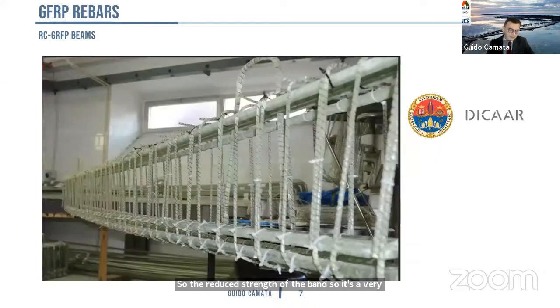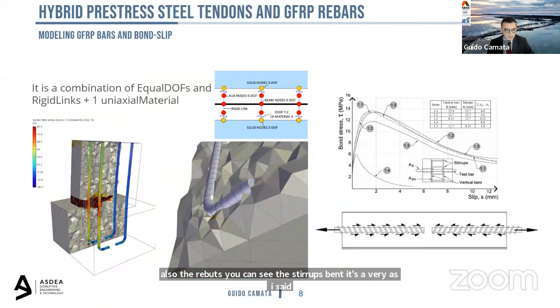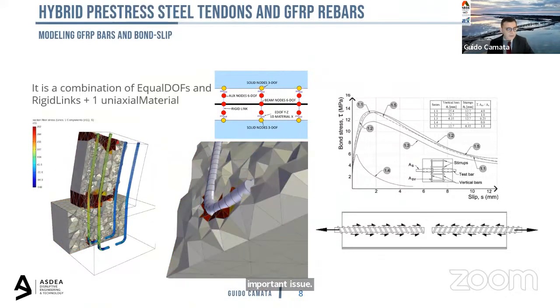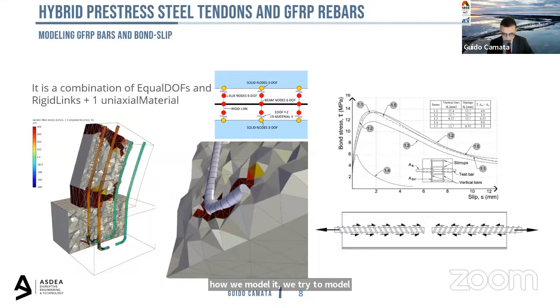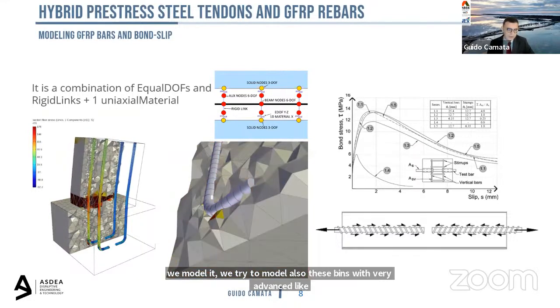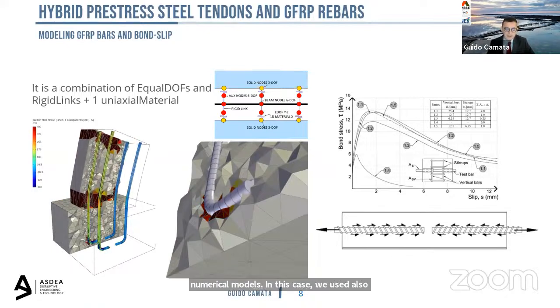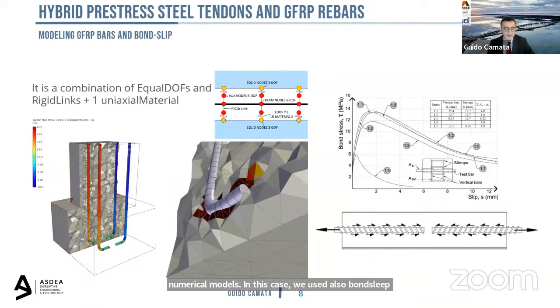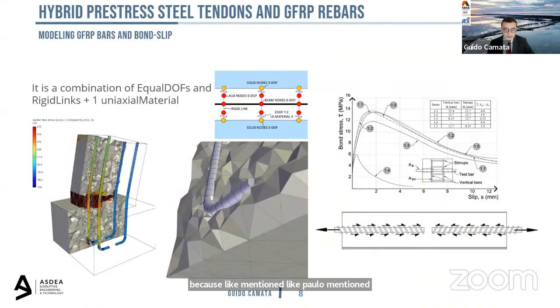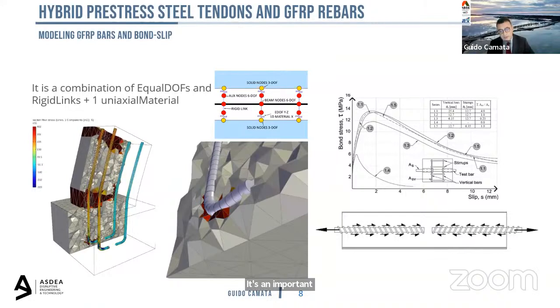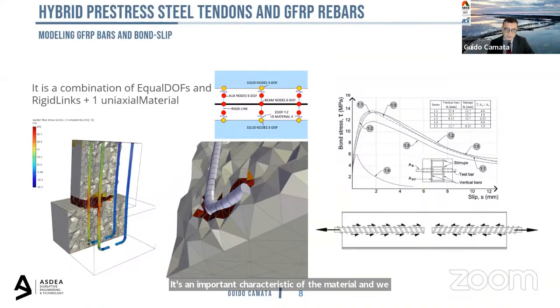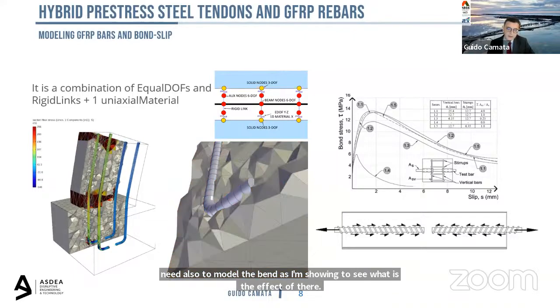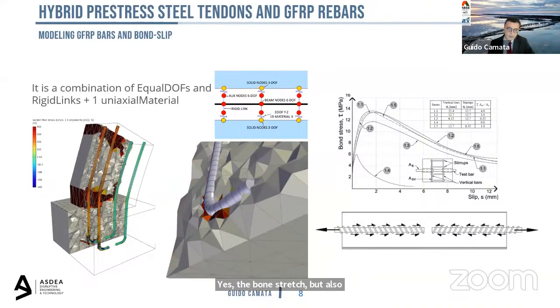So you see, this is a cage, as I said, completely made of GFRP. And also the rebars, you can see the stirrups bend. That's, as I said, an important issue. How do we model it? We try to model these beams with very advanced numerical models. In this case, we used also bond slip, because like Paolo mentioned, it's an important characteristic of the material. And we need also to model the bend, as I'm showing, to see what is the effect of the bond stress, but also the effect of the bend on the performance.